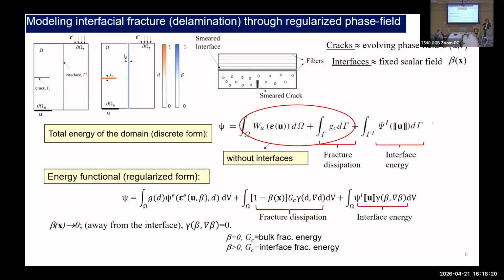So even without any crack at the interface, just because of this mismatch of fiber orientation, there is a displacement discontinuity along those interface surfaces. Okay, so any sharp discontinuity again troubles our continuum mechanics approximation and the solution. So what we did is, just like the phase field approximation, we used another smoothing scheme to smoothen out these sharp interfaces. So we had d previously to describe the sharp crack. Now we have beta, which is also a phase field variable. The difference between d and beta is that beta does not evolve with time. So it's a fixed scalar smoothing variable, which varies again between 0 and 1. 0 represents the bulk material, 1 represents the sharp interface.